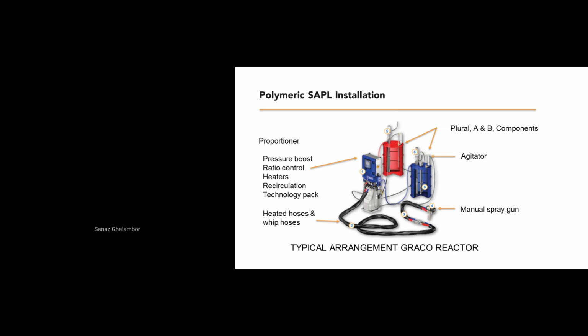As mentioned before, the system cannot be used with regular methods like conventional sprays or brush or roller. So this is the reactor or proportioning unit that we use to apply the system. Because the reaction time is very fast, the A component and B component, or resin and hardener, should be kept separately until they mix right in the gun at the nozzle. And as soon as they are mixed and sprayed, they gel and dry in a few seconds.